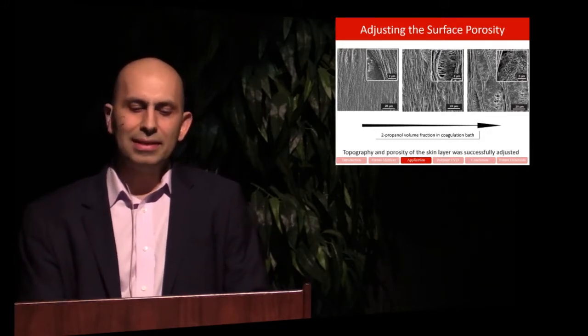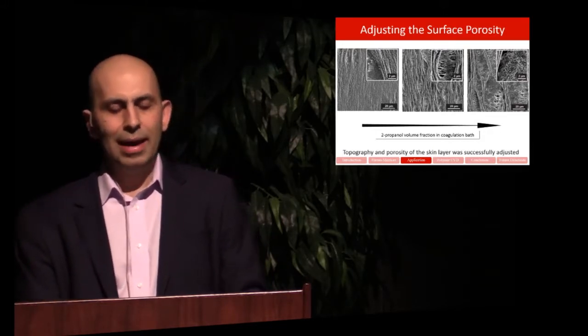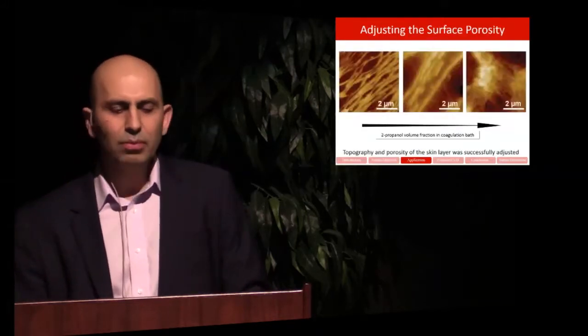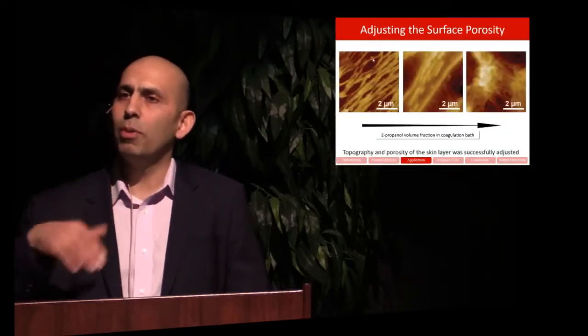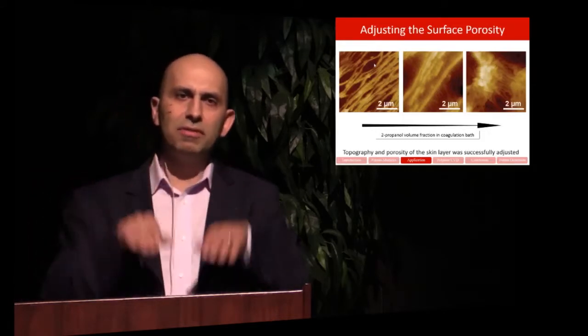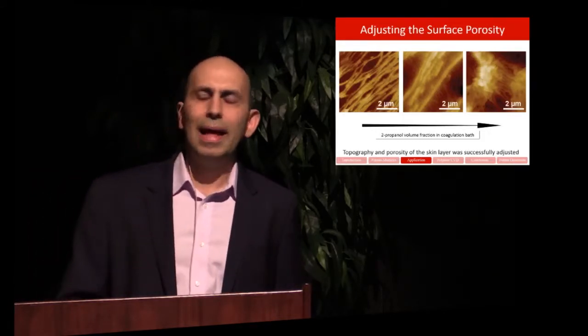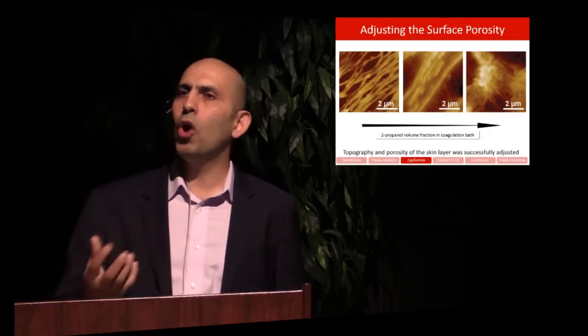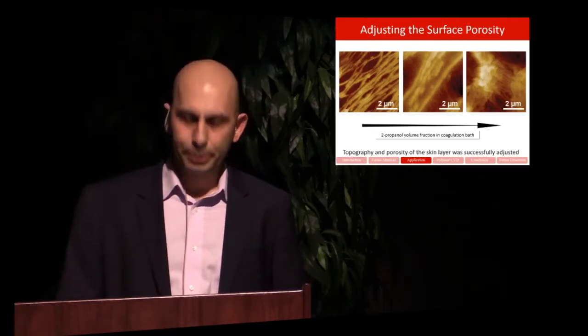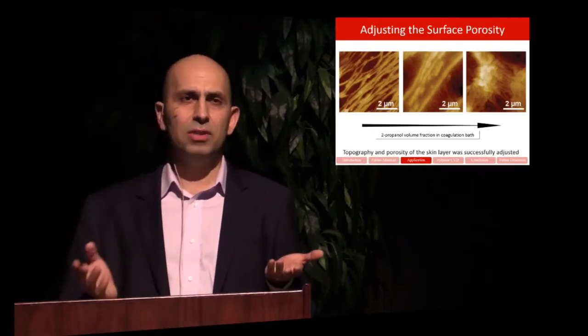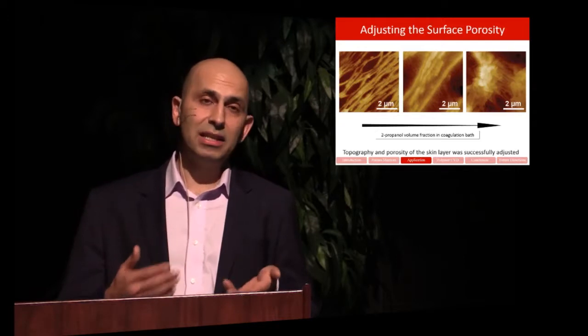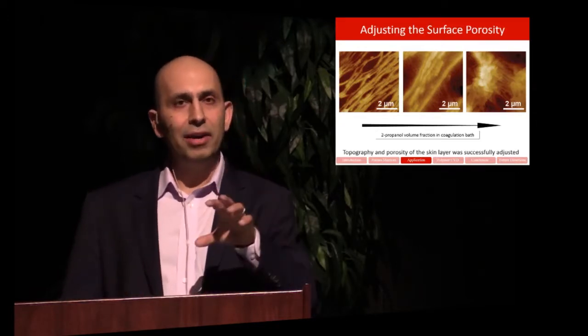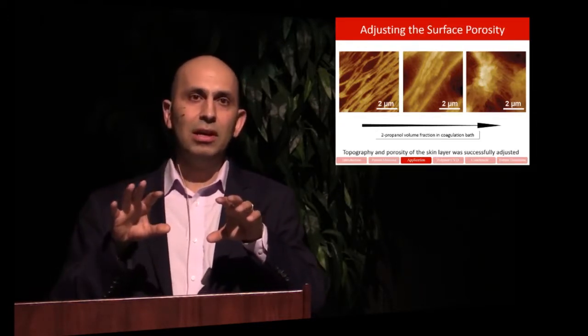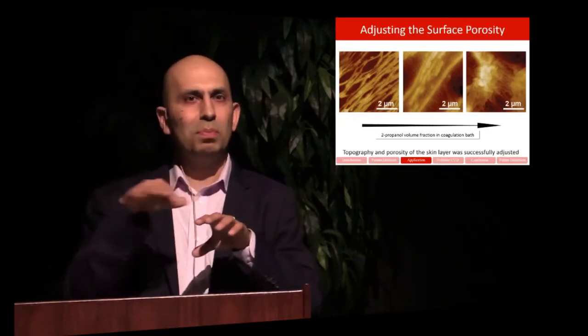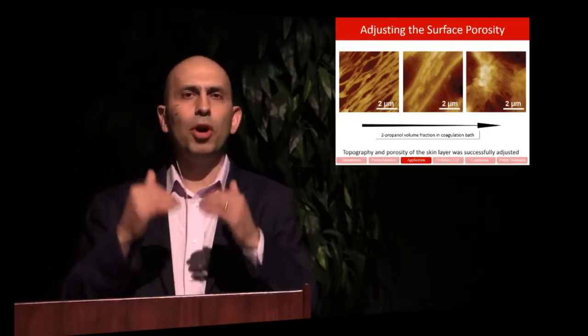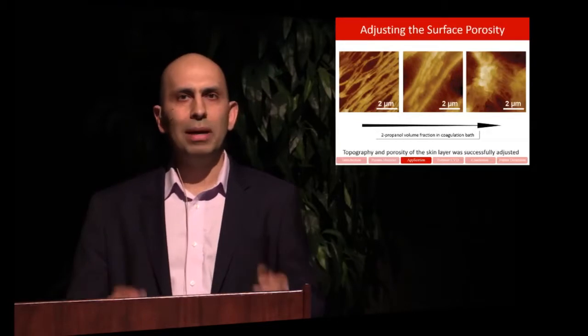It turns out that the same action results in changing the surface topography. Basically, the height of the surface is changing. And that has an effect on how the water interacts with the surface. So if you have a surface which has significant heterogeneity, you have air and you have surface on it, air can sit behind or occupy the place where the water can sit. As a result, it's going to repel water.